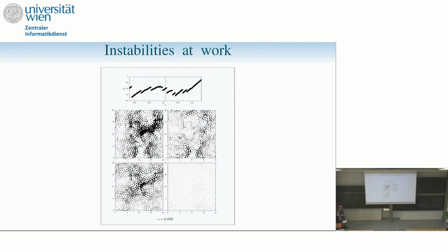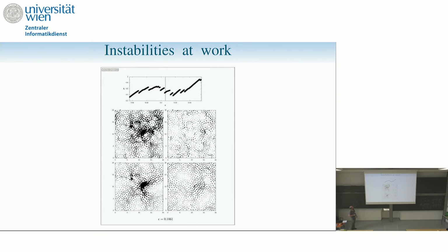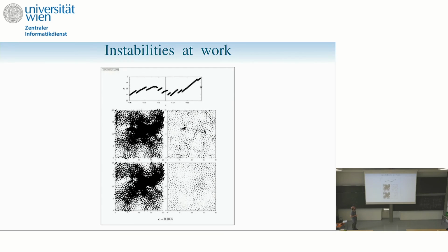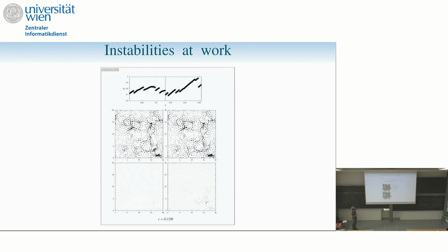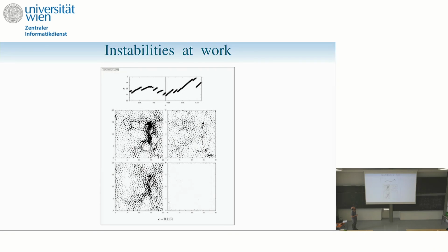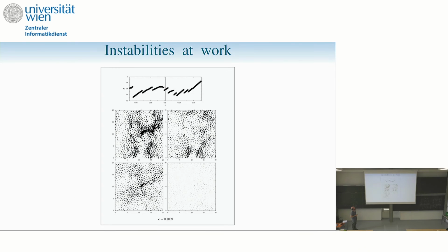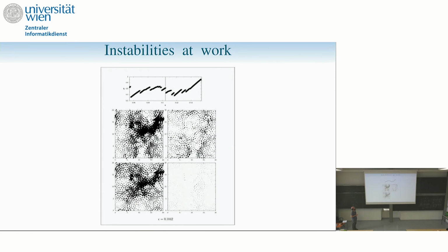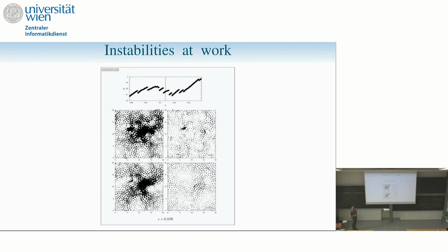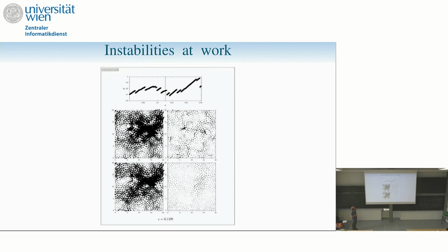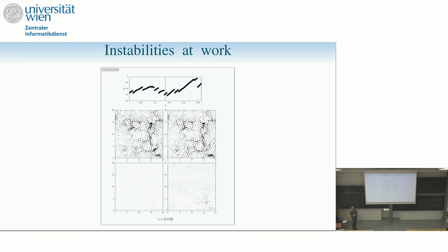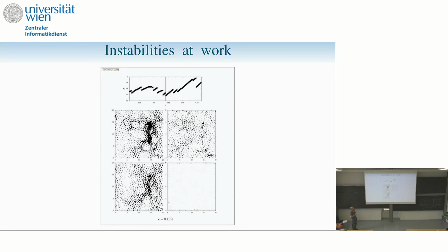Okay, so instabilities at work. This is a video. This is the non-affine field as we approach instability. So it's a short movie. Let me start again. So what you see is that when you approach an instability, boom, you have this non-affine field that localizes on the unstable mode, and maybe something here, and then another instability. And after the instability, the system is much more stiff. You see that after instability, you have stiffened your system. But you see these dynamics of the system going through instabilities and localizing every time.